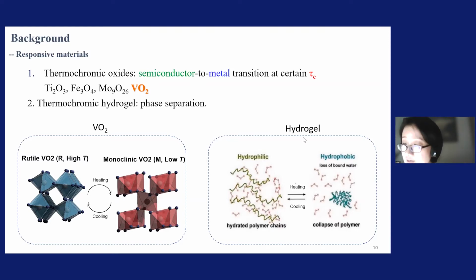And the other one is hydrogel. Why do people use hydrogel? Nowadays a lot of research groups have used hydrogel for all sorts of different things. We use hydrogel because it requires a phase separation. If you heat up, some of these polymeric chains are going to collapse out of the water. In my research field, I want to use this collapse of the polymer, because then it serves as a scattering center to scatter the light. So we use a phase separation. You can say these two work with different mechanisms: VO2 is phase transition, and hydrogel is working with phase separation.